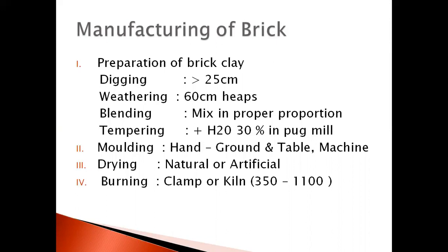The third sub-step is blending — mixing all the ingredients in the proper proportion. A mixer can also be used for blending. The fourth sub-step is tempering — after blending, the mixture is like solid particles and can't be molded, so we add water equal to 30% of the weight of the soil in a pug mill. This is known as tempering. So the four stages of preparing brick clay are: digging deeper than 25 cm, weathering with heaps of 60–120 cm for weeks or months, blending, and tempering with 30% water.